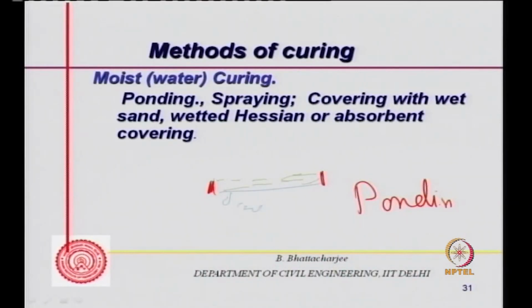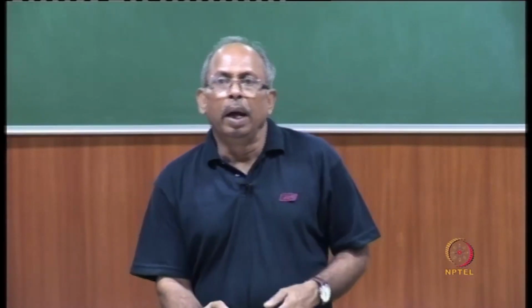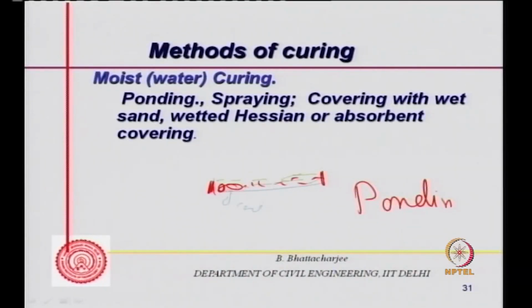Spraying, spray with any kind of pipe, and then covering with wet sand. Instead of ponding, you can put sand particles here, and this has to be maintained wet. Or you put wet Hessian cloth or absorbent covering. This could be for slabs or for columns also. For example, if it is a column, you can put wet Hessian cloth here, which will remain wet all the time. So you keep it wet with some kind of absorbent covering. This is how moist curing is done.